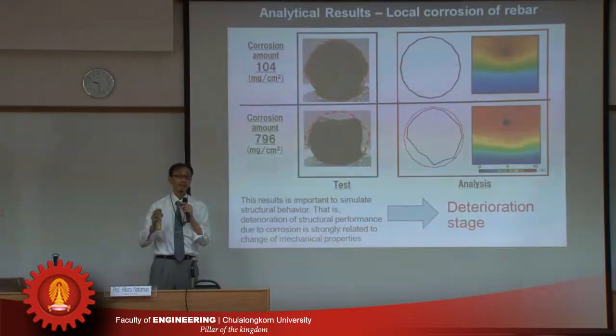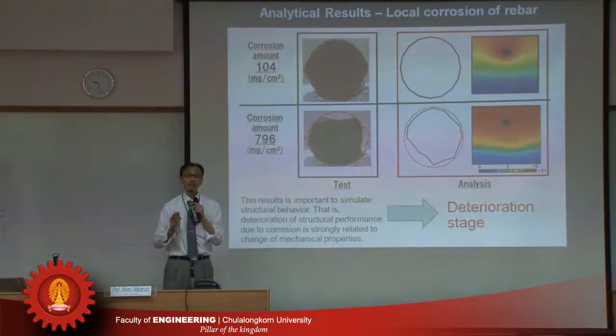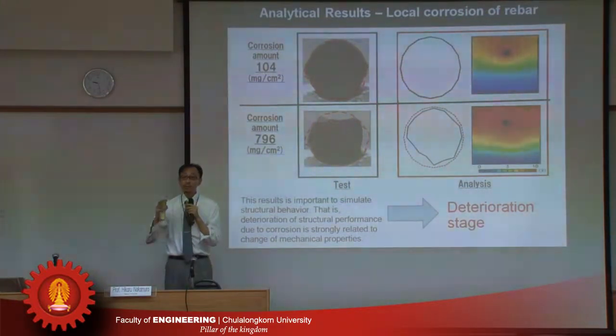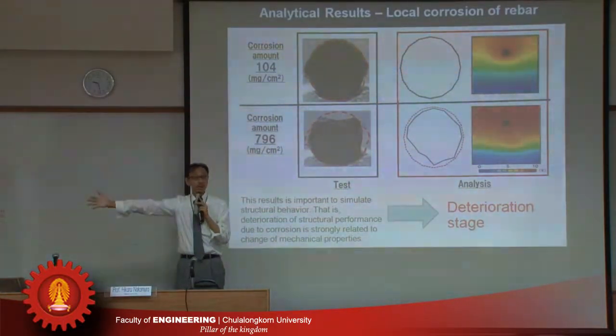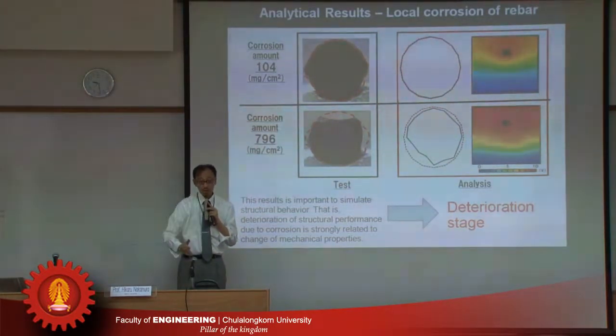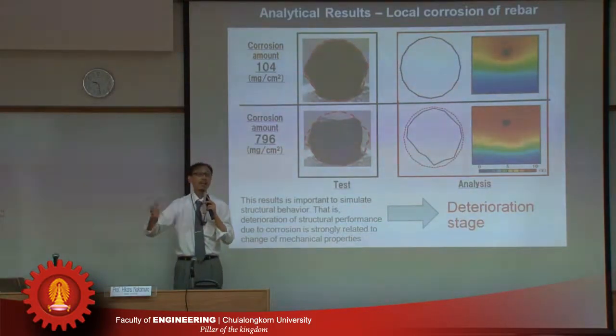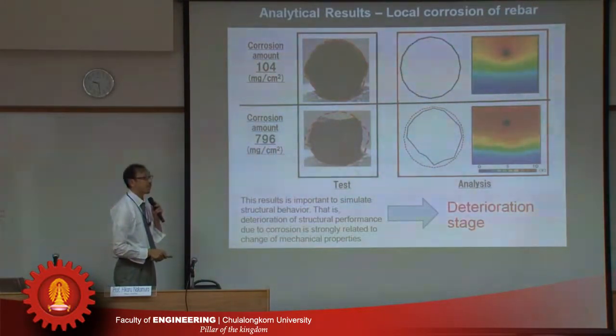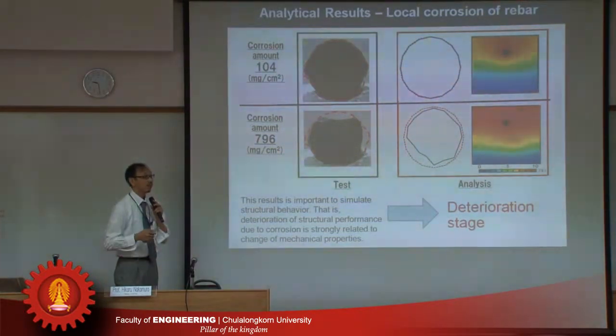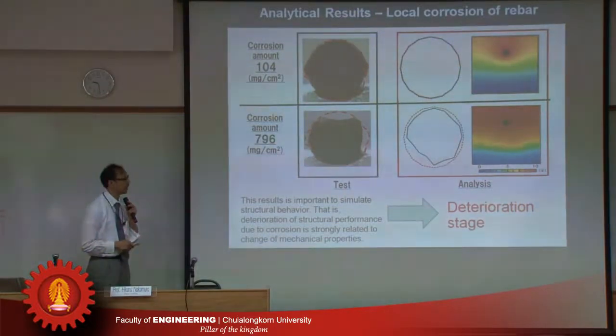What is the problem of corrosion to concrete structures? Of course, cracking is a problem, but the most important problem is that after corrosion, the mechanical performance of the reinforcement deteriorates — yield strength deteriorates, extension ability becomes small, and sudden failure occurs. So we would like to simulate this deterioration stage. Using this result, we can simulate the deterioration stage and the deterioration process of the rebar directly. This is an important point of this method.